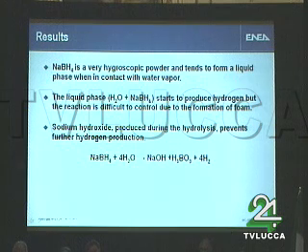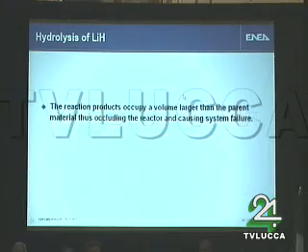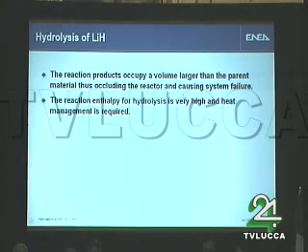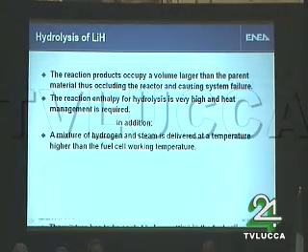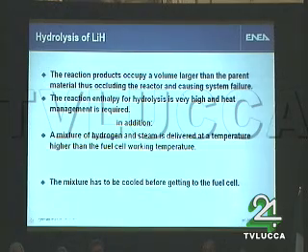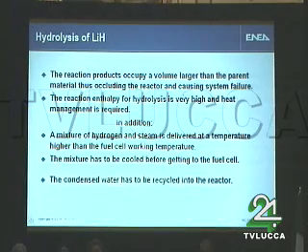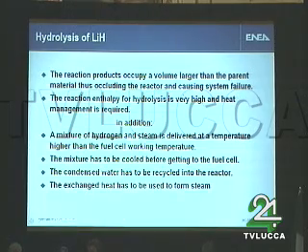Also, the sodium hydroxide that is produced during the reaction stops the reaction itself, and so we encountered a lot of problems. In the case of lithium hydride, we obtained another problem, that the volume of the reaction products is larger than the volume of the parent lithium hydride. So in some cases there is a reactor occlusion, and the reaction enthalpy is very high, and so we need to refrigerate the reactor. And other technological problems have to be solved.